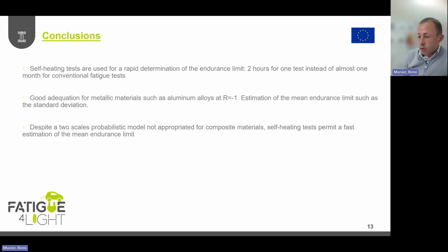And then we have also tested composite materials. We have shown that there was only one primary regime, and when we have a progressive appearance of microplasticity, there is directly a failure of the specimen. And then the estimation is quite good also for the mean endurance limit. Here I haven't presented the result, but when we compare the self-heating method and the one obtained with the stiffness method for CFRP, we have quite similar results.